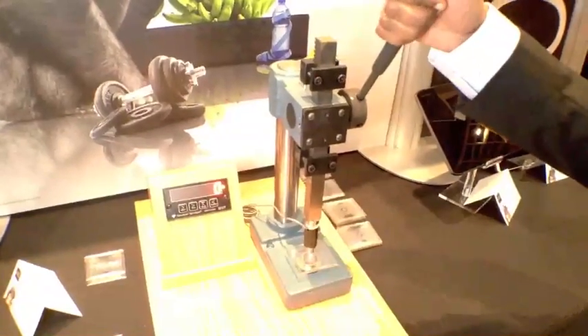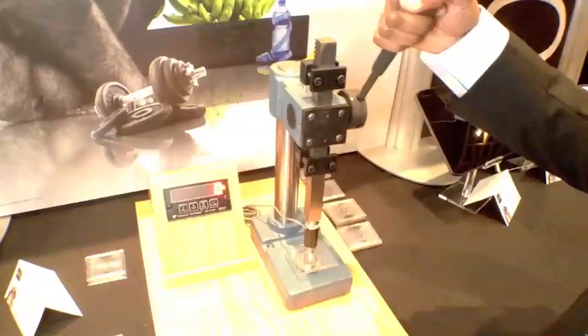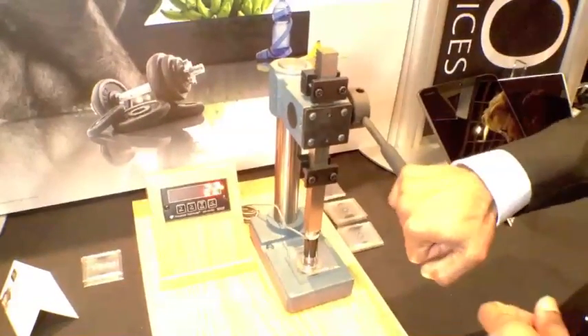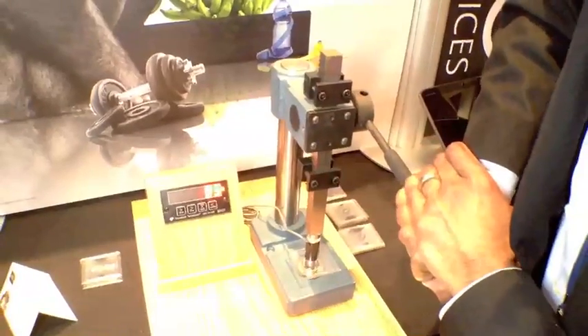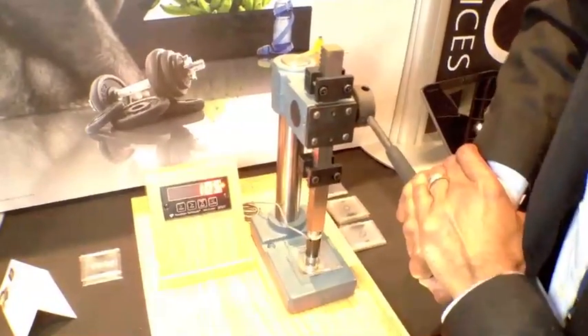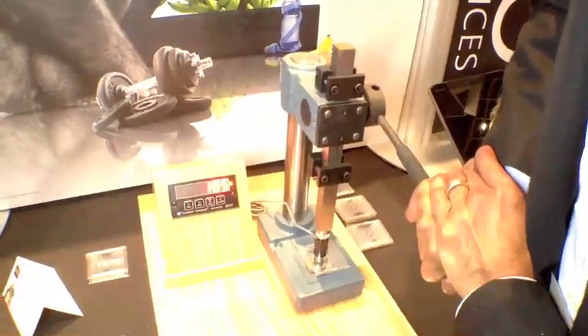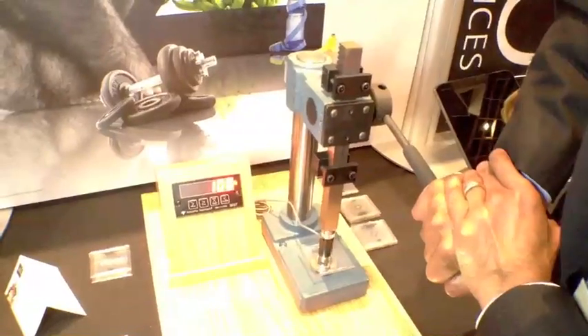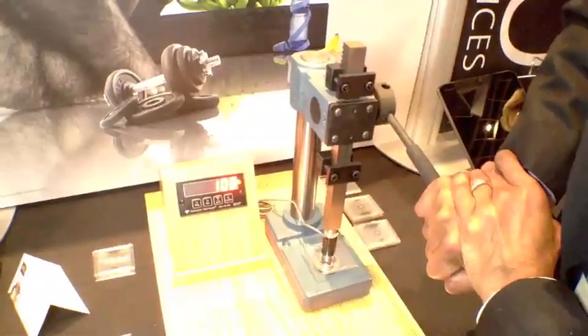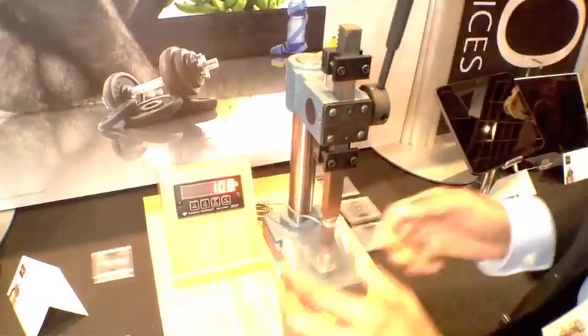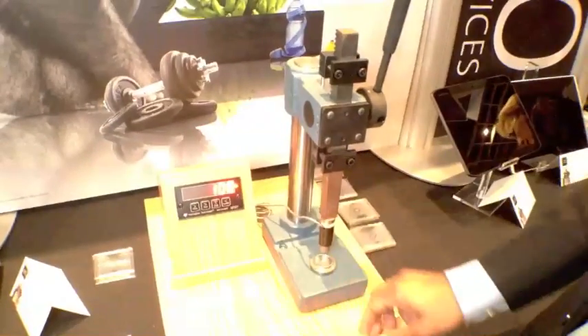Again, at 1 millimeter, it's already about 10% thinner than this glass over here. 105 pounds. 108. It can't break the glass. 1 millimeter Gorilla Glass.